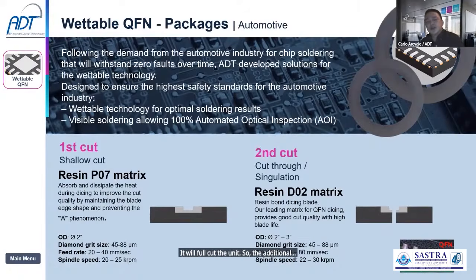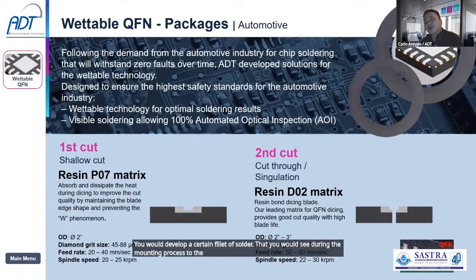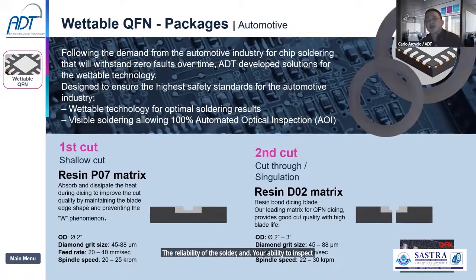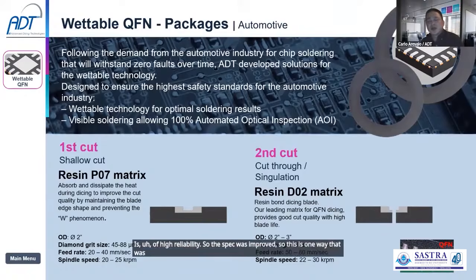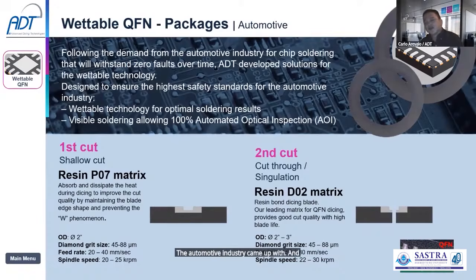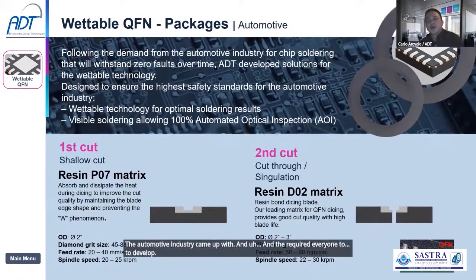So the additional plating that was placed after the first shallow cut was performed would help to show this. You see in the photo on the right bottom, you would develop a certain fillet of solder that you would see during the mounting process to the board. So one of the things that is improved here is the reliability of the solder and your ability to inspect the units easily and fast compared to the X-ray or the AOI that they do. For automotive devices, there's a requirement to ensure that the solderability is of high reliability. So the spec was improved. So this is one way the automotive industry came up with and required everyone to develop what they call the wettable QFN.